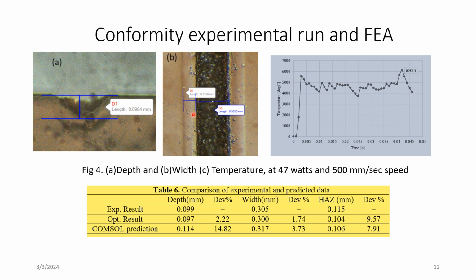This is the depth, width, heat affected zone, and the COMSOL profile shows the temperature with respect to time. The result shows that the experimental results closely match the optimization results. Individually, this is for the depth, this is for width, and this is the heat affected zone. The COMSOL prediction also closely matched the optimal results.